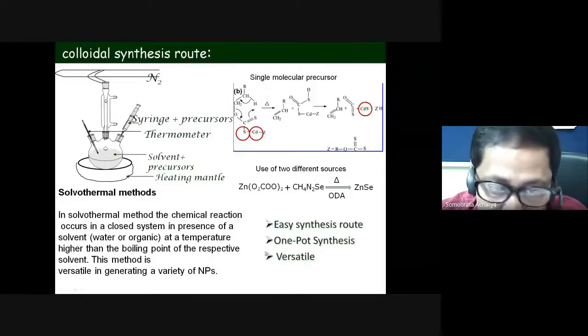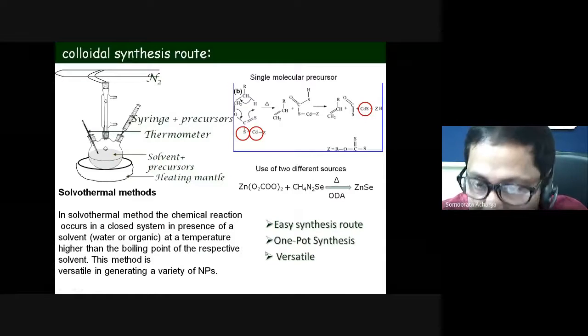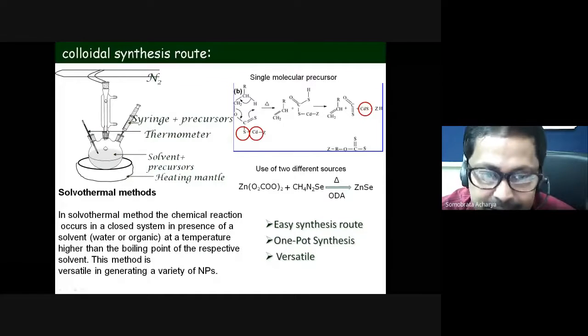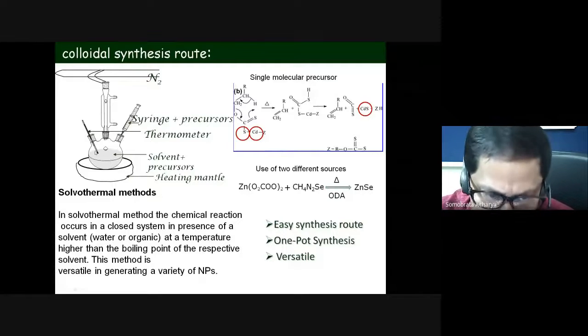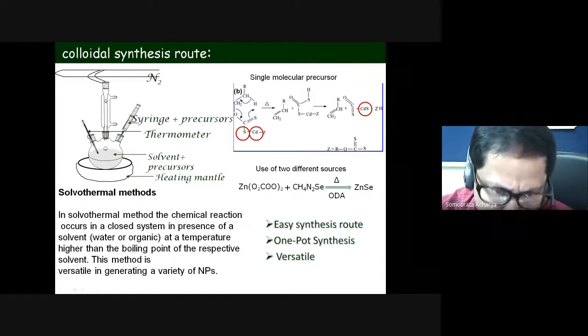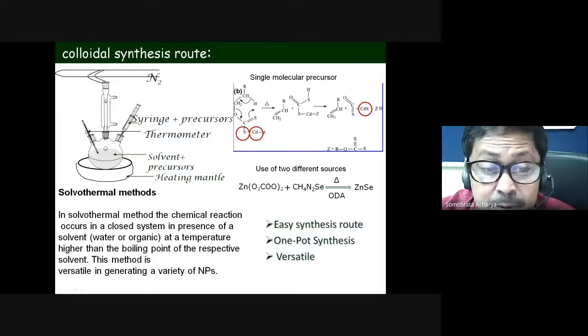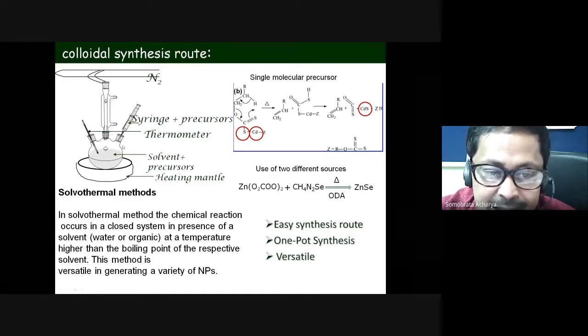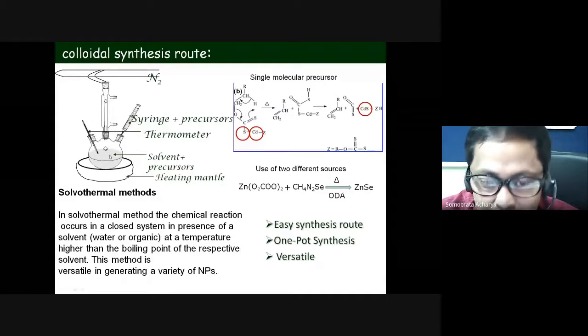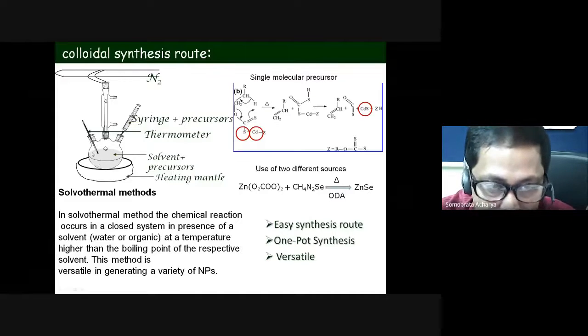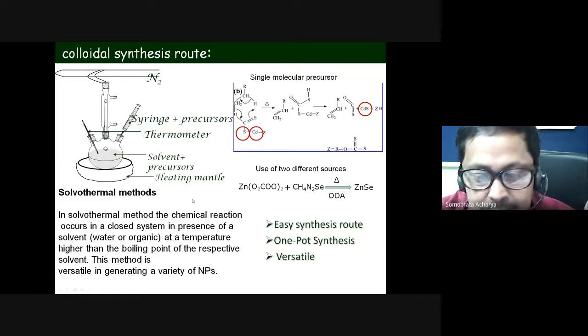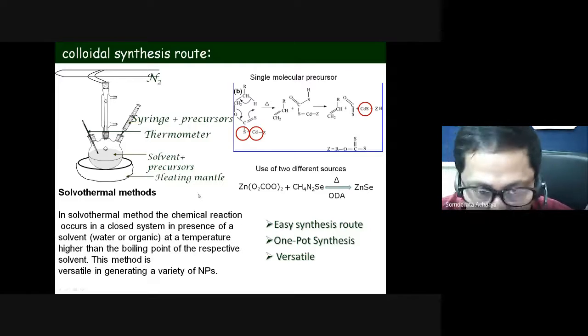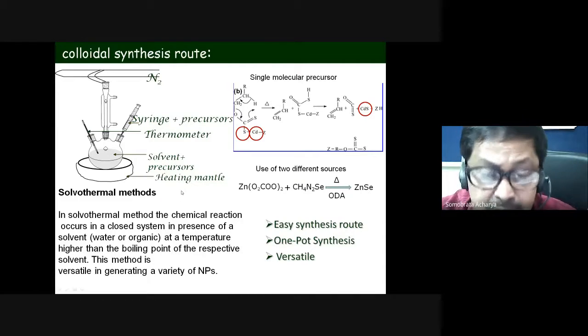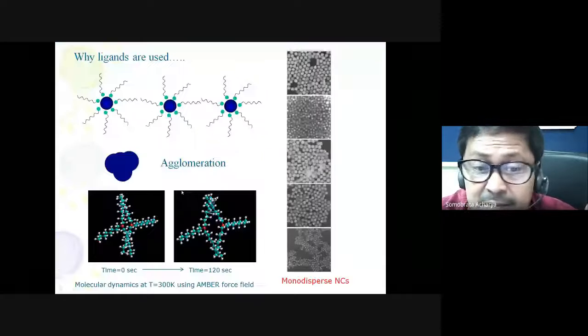So this gives you some idea of how solvothermal synthesis, that means synthesis in a pot, can be done. This is the typical setup. You have a beaker like this, then it has to be within an inert atmosphere. So you take all the reagents and solvents within this beaker, fix the temperature somewhere around say 100 degrees, and you can monitor that by means of a thermometer. And of course, you seal the entire system. And if you want to inject something additionally after that, you use a syringe. The entire system is within the inert atmosphere because you don't need other elements like oxygen to be there. So that's how one can use the colloidal synthesis route for the designing of these nanocrystals.